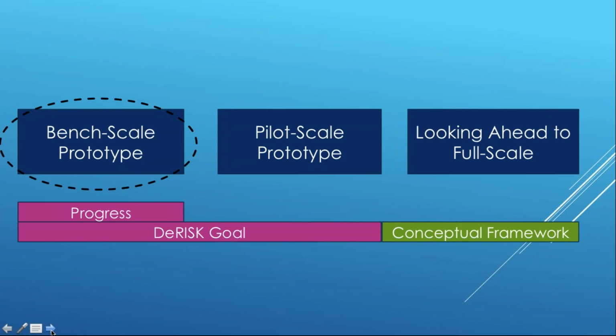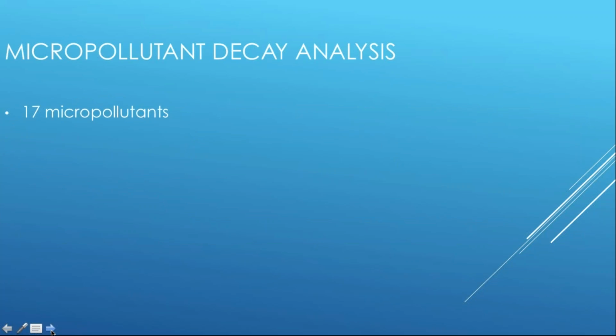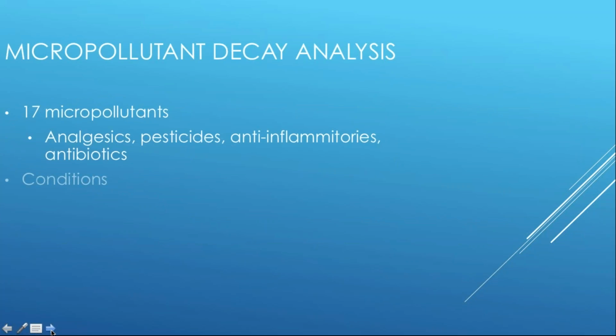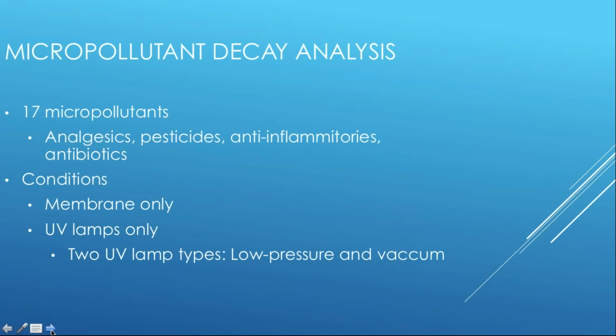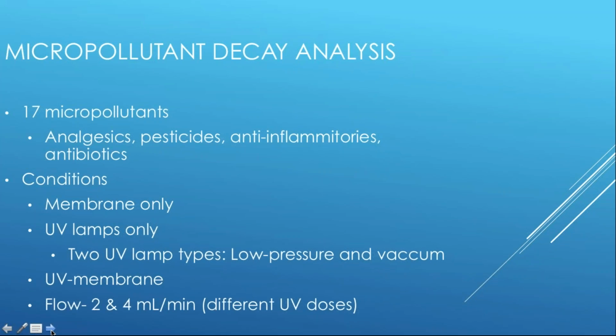These initial experiments led us up to our main experiment for the bench scale test, and that was a micropollutant decay analysis. We were just looking at parent compounds, but we looked at the parent compounds of 17 micropollutants, just a whole cocktail of them. We had multiple conditions, so we looked at a condition where we treated the water only with membranes, only with UV lamps, and that includes both low pressure and vacuum UV lamps. Then we looked at the combination of the two processes, and finally we wanted to determine maybe if UV dose could influence the decay of the micropollutants.